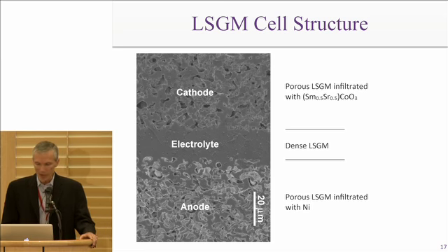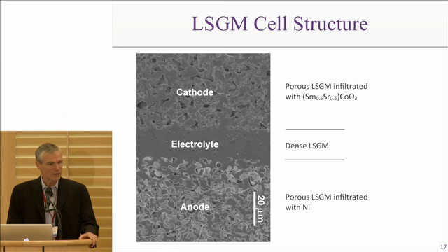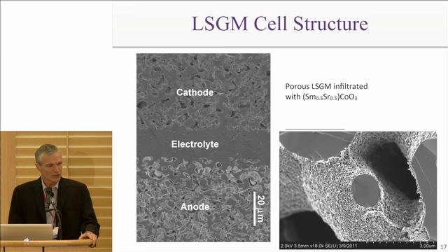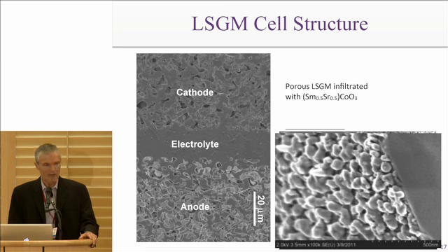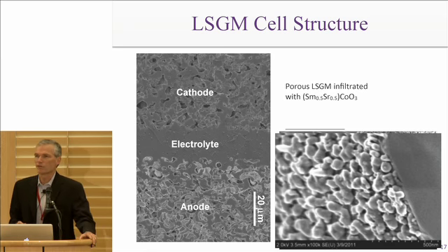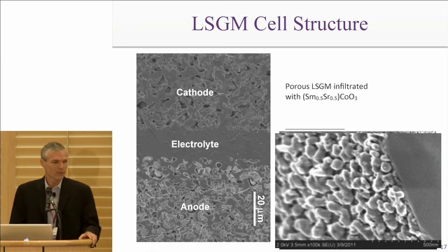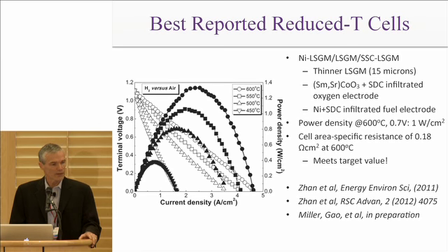This is just kind of a low magnification view of what the structure looks like, so you can see the porous structures of either electrode and a thin, dense electrolyte structure. Since you can't see this too well, I want to zoom in. And this shows, zooming into this anode structure here, you can see within the pores here, and you can actually see now a little bit of this nanoscale nickel structure on those, which provides highly active reactions. And this is an even higher magnification view, showing some of these particles are down to the sort of tens of nanometer scale.